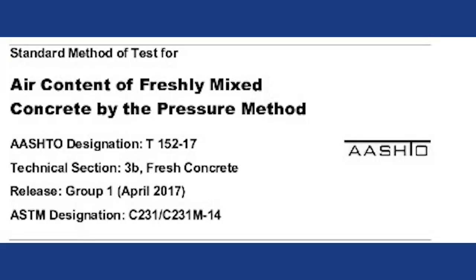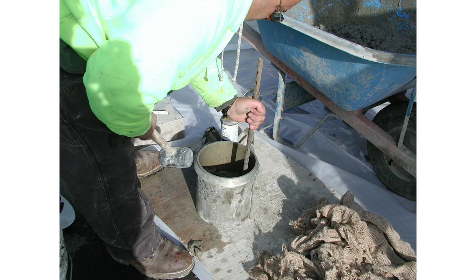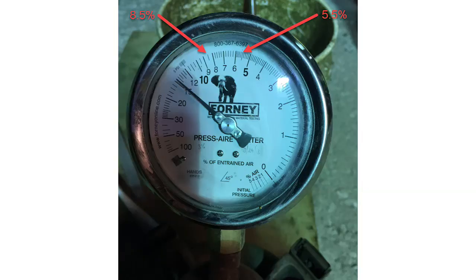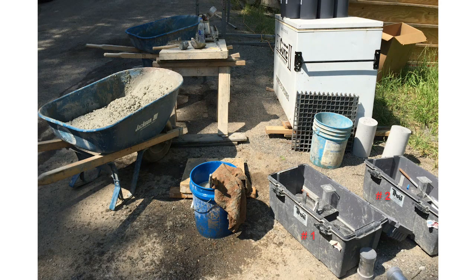Air content testing for bridge decks. Perform plastic air content testing in accordance with AASHTO T152 and as follows. AAAP concrete mixes are to have a plastic air content of 7.0% plus or minus 1.5%, which is a range of 5.5% to 8.5%. Two sets of calibrated air meters are to be available at each concrete placement on the project, with one set as a backup.